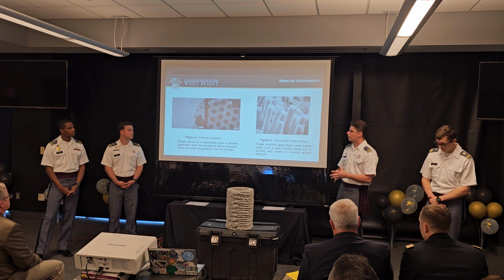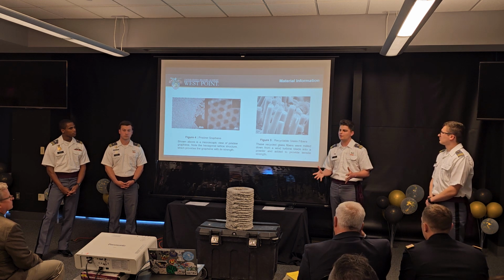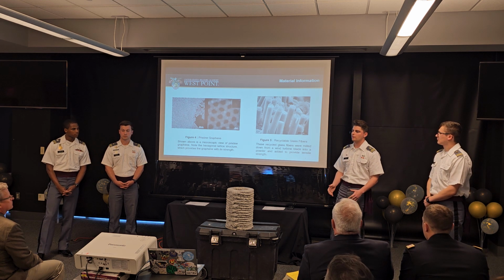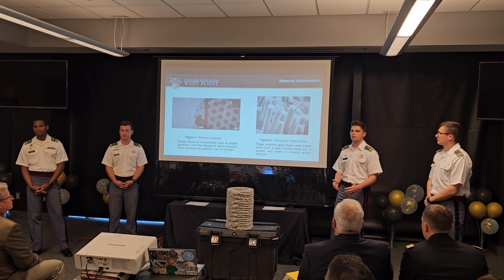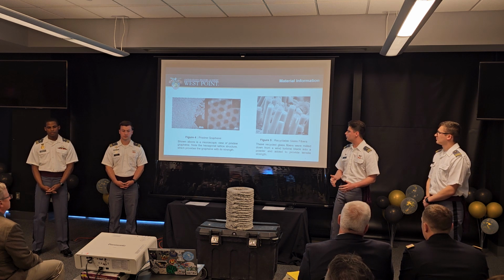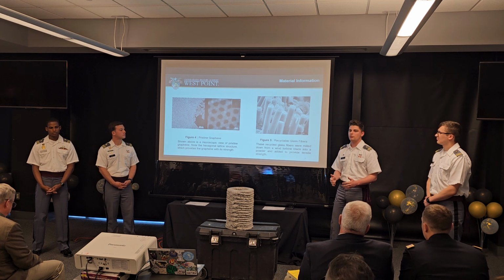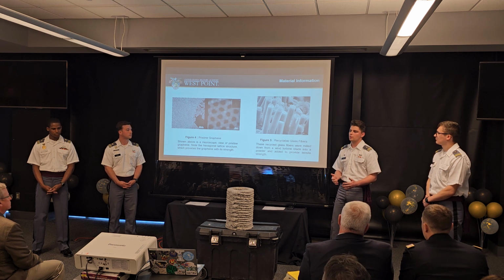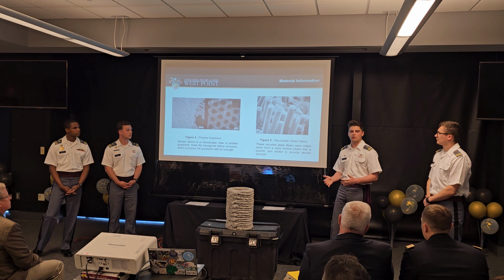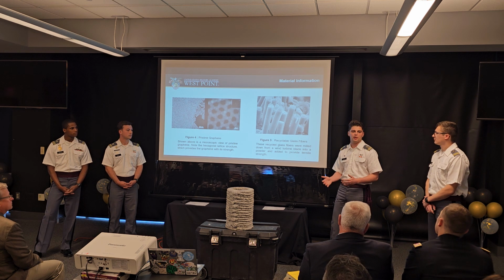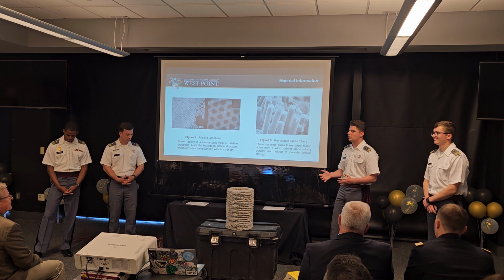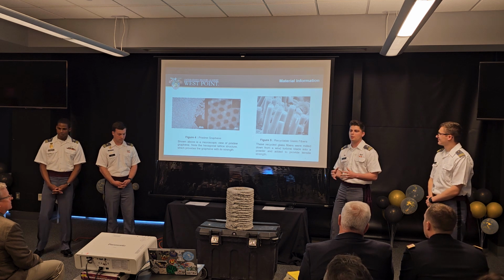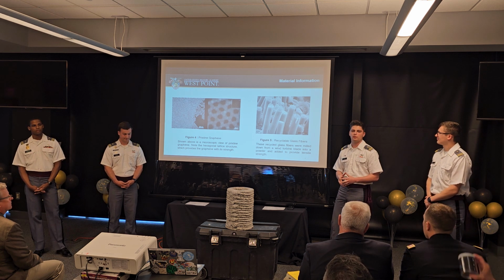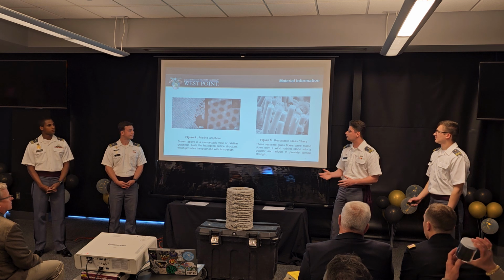Glass fibers, throughout testing, we were able to kind of figure out that it wasn't the most feasible based off of our current mix design, and we're looking to do more research into this in the future. It was originally supposed to be added as a way to incorporate eco-friendliness. The fibers were obtained through the milling of wind turbine blades, which would have otherwise been thrown away. And they essentially act as mini rebar within the concrete and help reinforce against tensile, which is typically the weakest part of concrete.